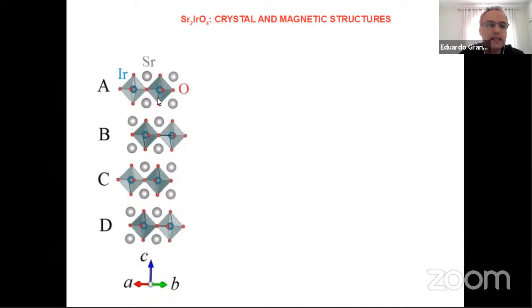So in principle, we have the iridium in blue, which is surrounded by the oxygen octahedra that I mentioned before, because it generates this octahedral crystal field of oxygens. And the strontium atoms are outside this network of iridium oxygen. So we have these layers A, B, C, and D, which are packed in the C direction, and that's pretty much it. And also you have this tilt of the